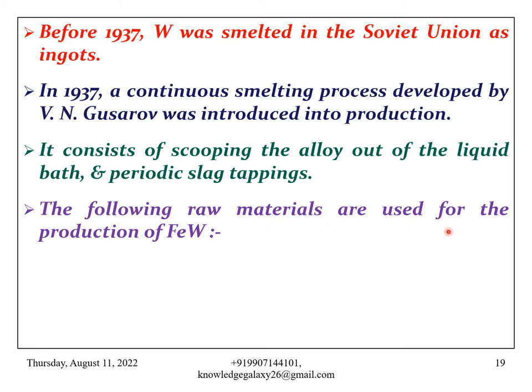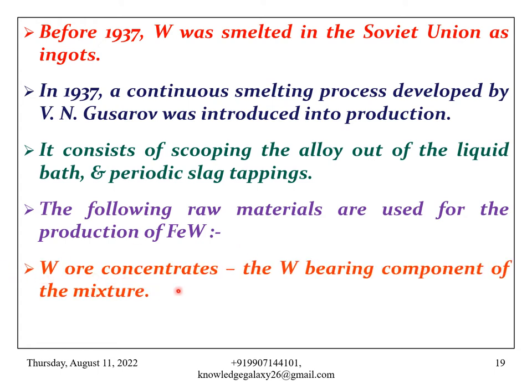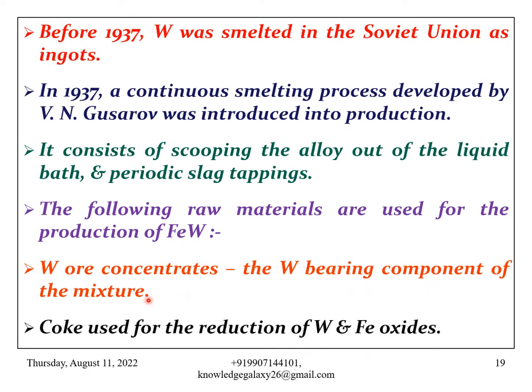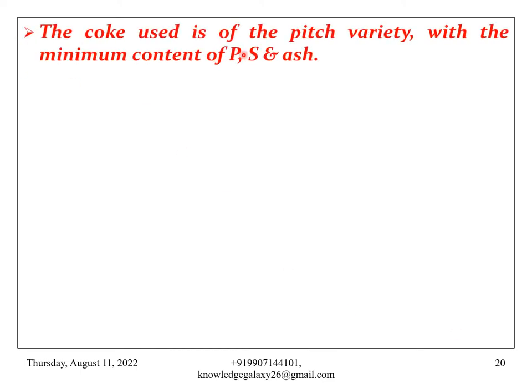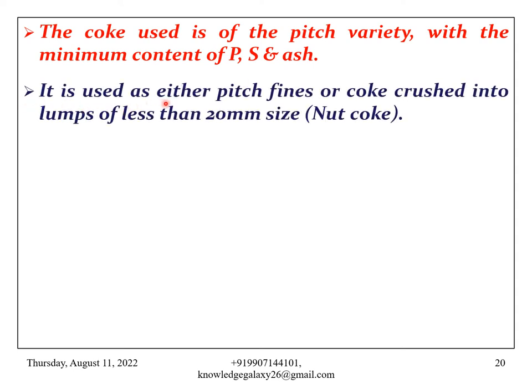The following raw materials are used for the production of ferrotungsten. First, tungsten ore concentrates. They are the tungsten bearing component of the mixture. Next is coke, used for the reduction of tungsten and iron oxides. That is, coke is the main reducer. The coke used is of the pitch variety with the minimum content of phosphorus, sulfur and ash. It is used as either pitch fines or coke crushed into lumps of less than 20 mm size. It is popularly known as nut coke.